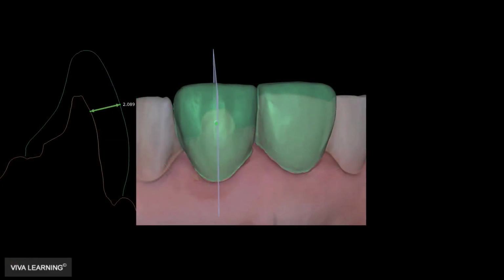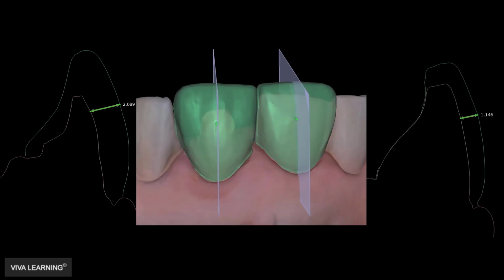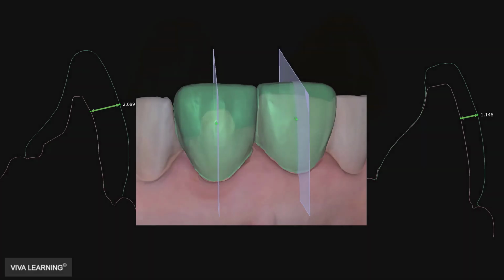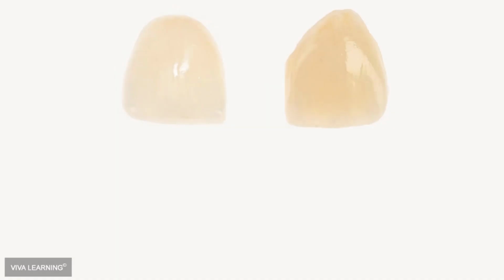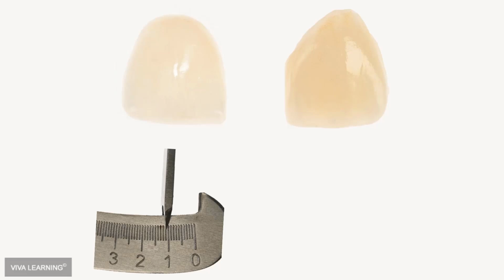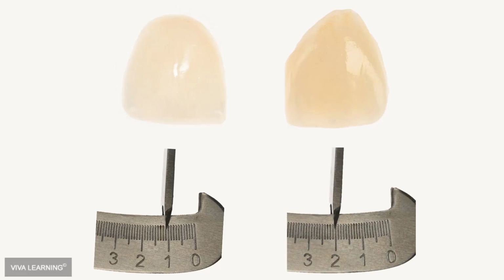So if we do a cross section of tooth number 9 with a crown on it, superimposed to the previous restorations, we can see that it was 2.1 millimeter thick, but the veneer was just 1.1 millimeter thick. So this difference in thickness will also be translated to the restorations we will make. You can see that these two restorations look different. It seems that they're of different shades, and that dominantly comes from the fact that one of them is only 1.1 millimeter, and the other one is almost 2 millimeter.